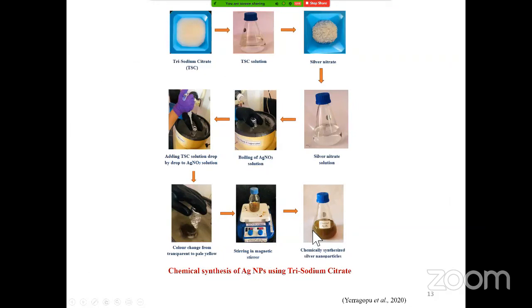And this is chemical synthesis of silver nanoparticles using trisodium citrate. This has been a part of my PhD research. I have taken silver nitrate as a metal precursor, and trisodium citrate as a reducing agent. Here I have used heating and stirring method in place of a stabilizing agent. So silver nitrate solution and trisodium citrate solution have been prepared.